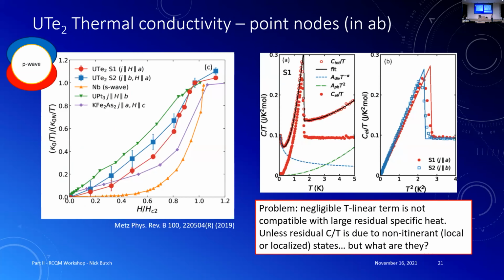So I guess saying that, okay, the red and the blue are UTe2. This is niobium, so this is S wave, okay? Then you've got UPt3, which is one of the weirder field dependences. And then this is potassium iron arsenic. And so the field dependence of this looks unconventional. It looks nodal, okay? So again, I have this picture here. It's a vestigial remnant of an earlier talk where I was actually focusing a little bit on the other measurements that support the presence of nodes. So things like microwave, and also just the temperature dependence of NMR are also consistent with it.